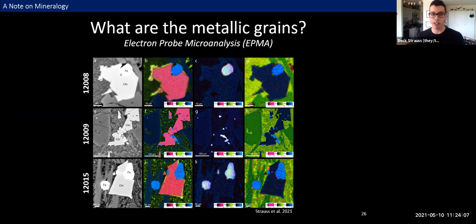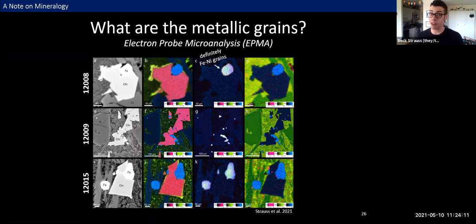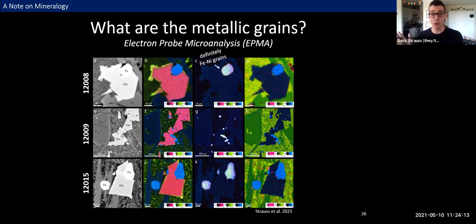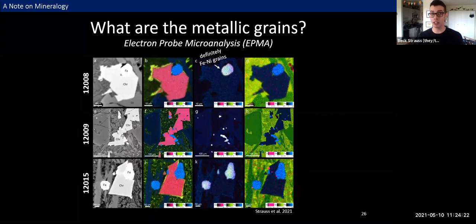So what we can tell from just this subsample of our images is we've definitely got iron nickel grains in these samples. Cool, very exciting. More exciting are some other features of these grains that we noticed. First, we found grains with different iron nickel ratios within each sample, and we were able to identify both kamacite and taenite based on those ratios.